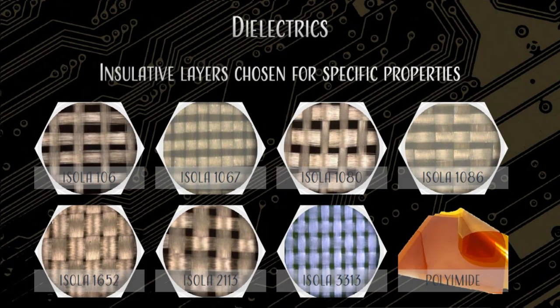We can stack them to get a higher depth. The thing with lasers is that they're actually an angle drill. It's done with a laser drill, and when it hits the bottom pad, it's smaller than it is at the top pad. So we have a rule that it has to be a 1-to-1 ratio. If you have a 6 mil hole, you don't want the dielectric from the top to the bottom to be any bigger than 6. All right, let's go ahead and move on. Thanks, Teresa. You're welcome.